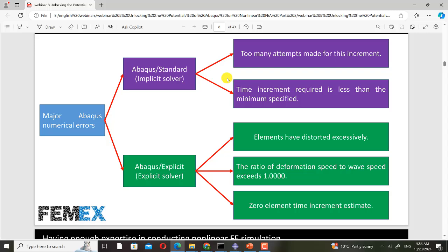But your changes and modifications on the numerical settings must not violate the physics of the problem. For example, if the loading is dynamic, you must not change it to quasi-static loading, because it is the physics of the problem. And about Abaqus Explicit, we have errors like elements have distorted excessively, the ratio of deformation speed to wave speed exceeds 1, and zero element time increment estimate. The major errors of these two solvers are different because their mathematical procedure is different. And each of them has their own advantages and disadvantages.